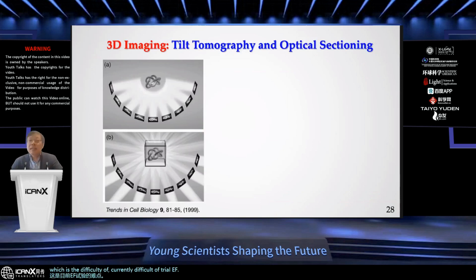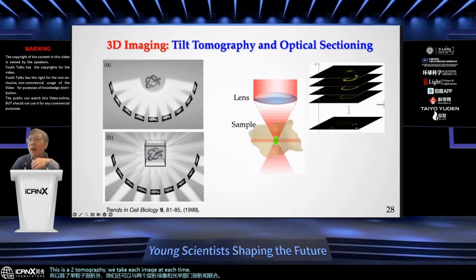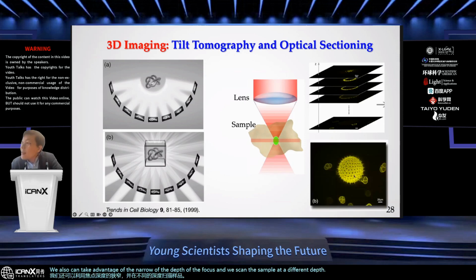Apart from single particle analysis, we also can combine with tilt tomography and optical sectioning. This is tilt tomography. We take an image at each tilt angle of the sample, and we can reconstruct a three-dimensional image. We also can take advantage of the narrow depth of focus, and we scan the sample at different depths. We can also achieve three-dimensional reconstruction, which we call optical sectioning.